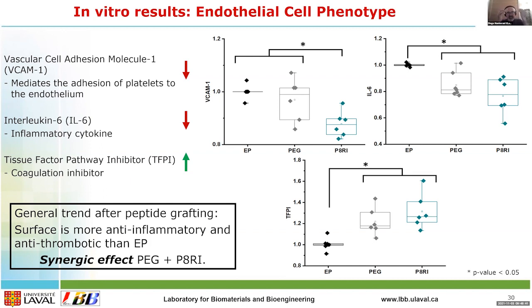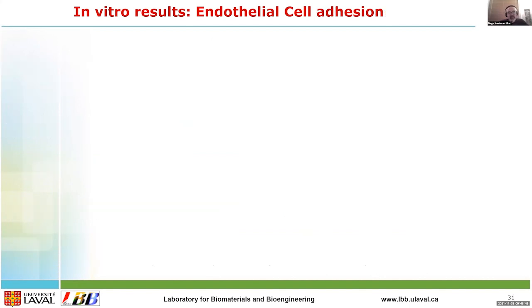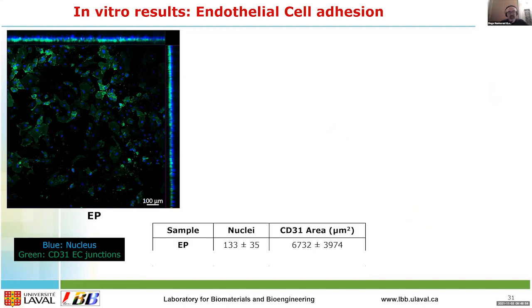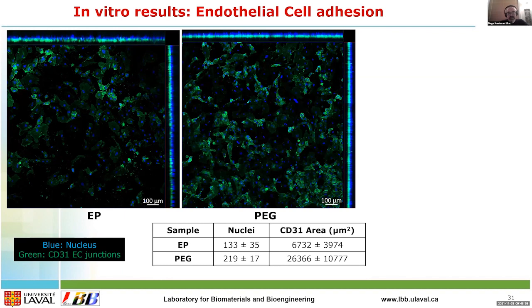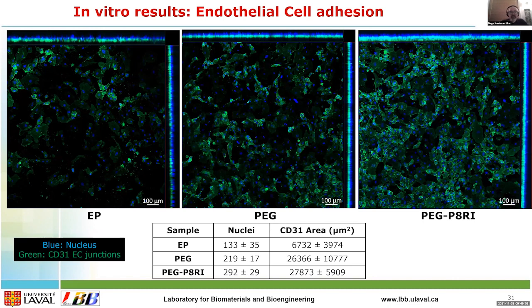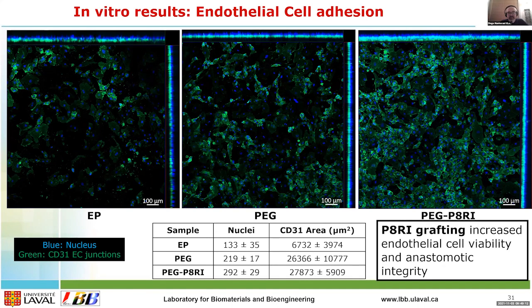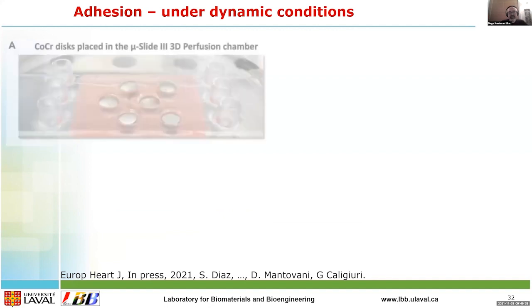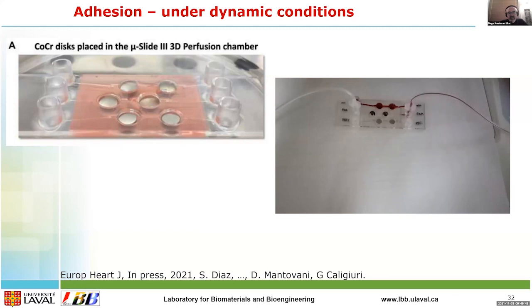What is interesting is that there is a synergistic effect between the PEG and the 8 peptides, the peptides composed of 8 amino acids. And then in vitro, you can see the endothelium on the electropolished surface, the pegylated surface, and finally the peptidic surface coating. As you can see here, in blue is the nucleus and in green is the junction between endothelial cells. Basically, you have a very increased endothelial cell viability at the anastomotic site, meaning closer to the connection where the stent and the artery are very proximal. You have an increased endothelial cell viability. So this was a coherent bunch of results that made us comfortable to run some tests under flow.